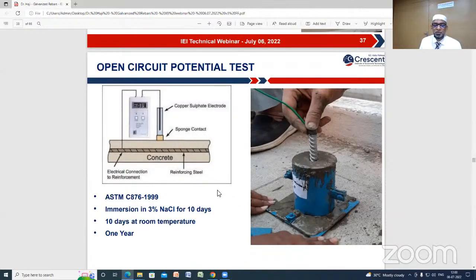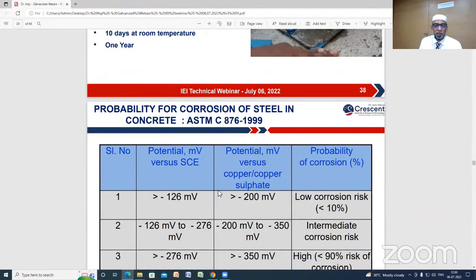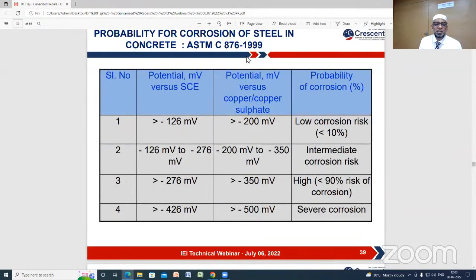We monitored the performance of the bar for 1 year. According to ASTM, if you use different electrodes, we have to interpret accordingly. Suppose you use a saturated calomel electrode: if you get a potential value between 125 and 275, it refers to intermediate corrosion risk. If you get more than 275, it refers to 90%. If you get more than 400, 425, then severe corrosion.